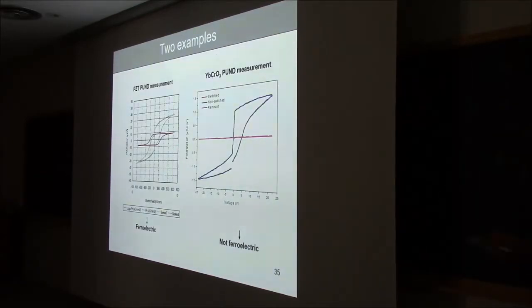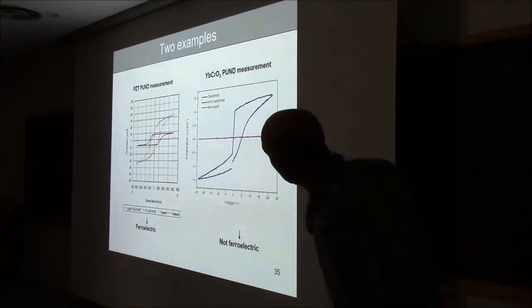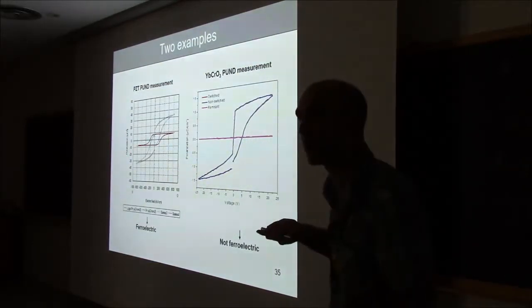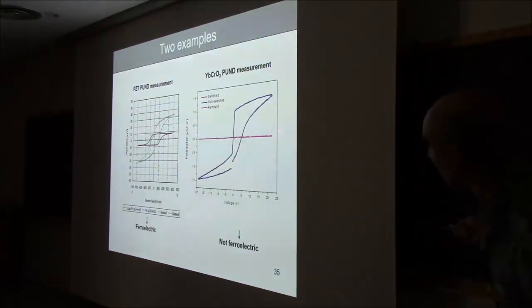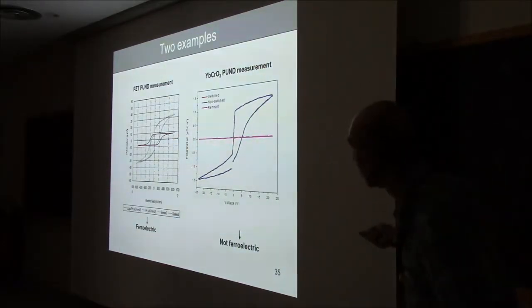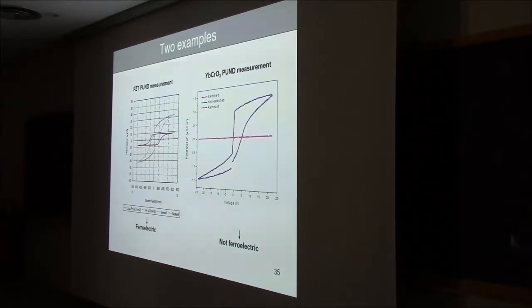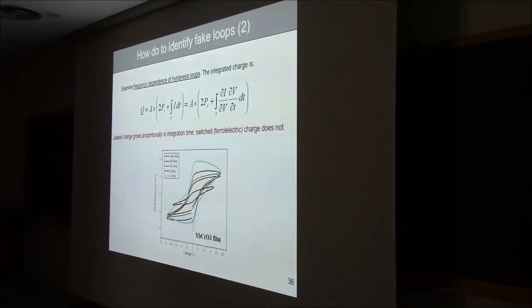Okay. And if you do this on a real ferroelectric, like PZT, after you switch, you get rid of the dielectric term, which is what gives you the slope in the hysteresis loop. And this is what a PUND loop looks like in proper ferroelectric PZT. And this is what our PUND loop looks like on our fake ferroelectric. I hate how the word fake has been spoiled by Trump, but anyway.